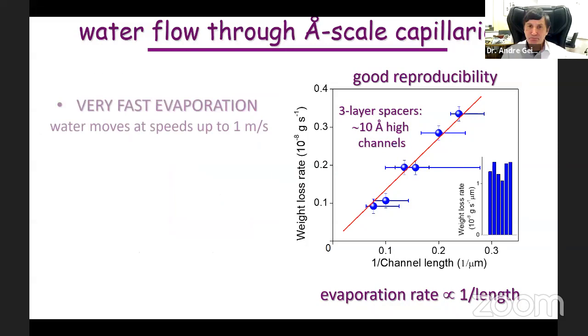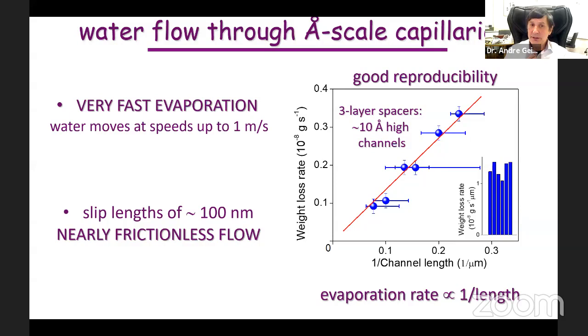When you talk about absolute numbers of evaporation, you immediately find out that it's an extremely fast flow. If it were a rough channel and so on, we wouldn't have enough accuracy to detect anything. So fortunately, our accuracy is enough just because the flow is extremely high. 1 meter per second through an angstrom-scale channel is really high. This translates into nearly frictionless flow. Slip length, for those who know what it is, is about 100 nanometers. It essentially shows that the friction coefficient is extremely low between water and the walls of those capillaries. Again, it shows their very high quality.